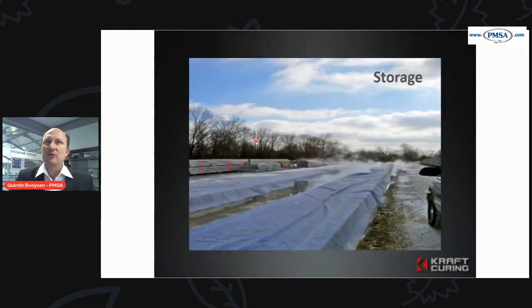Where it's not possible to have a storage system, we can use tarpaulins to protect the concrete and keep the heat inside. In a very cold environment, here you can see snow on the ground. The exothermic reaction underneath the sheeting may even be producing light steam, you can see the heat coming off it. That's through a proper curing solution, where in this case we may also have added external heat underneath, but we're maximizing that heat of hydration plus any additional heat by protecting and covering your concrete elements. Underneath here, you'll have these concrete elements.